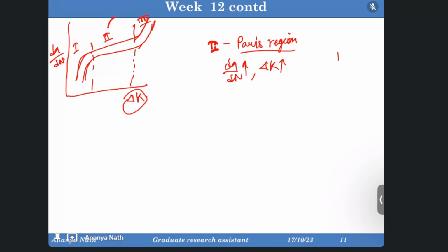It will have very high and rapid crack propagation. But up to the threshold value, the stress intensity will not be that much. There will be very minimal crack growth due to the stress that is getting developed inside it. Although these two graphs look the same, they are not the same. Here the crack growth is not that much, but here the crack growth is very high. Remember.